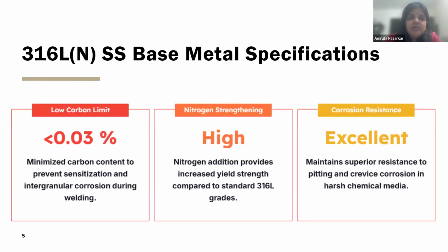Now, more about the 316LN stainless steel base metal, which is being discussed in this presentation. The 316LN stainless steel is basically low carbon. L is for low carbon and N is for nitrogen enhanced. So it has some amount of nitrogen and a low carbon. Low carbon is below 0.03%, and that prevents sensitization, and the nitrogen enhancement gives more yield strength compared to the standard 316L grades.